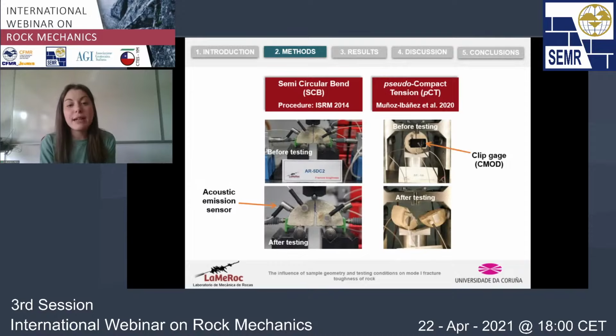These are just a couple of examples of the specimens before and after testing. We see that here after the test, there is a fracture that has developed. Maybe it's not that clear here on the SCB sample, but here we can see it clearly in the case of the PCT that there is a fracture that has propagated along the vertical plane. And for the PCT, we have also measured the crack mouth opening displacement. In this case, we used a clip gauge for this. And we have also recorded acoustic emission activity using sensors placed here on the surface of the sample.